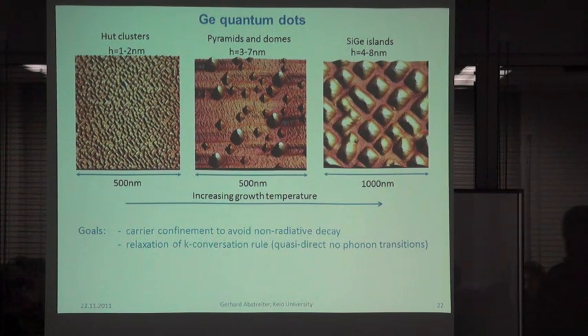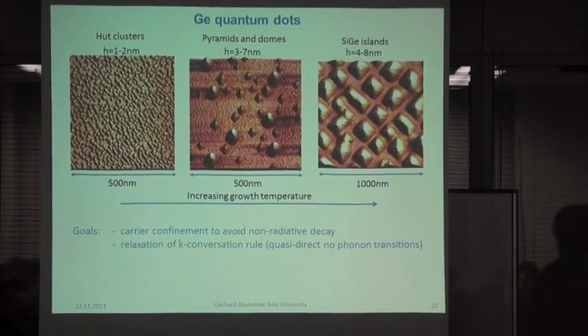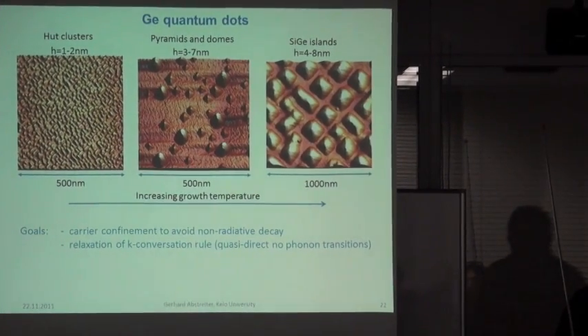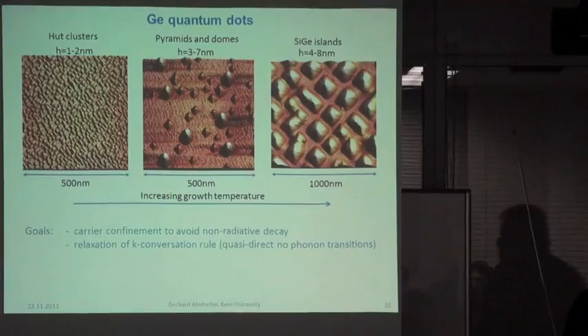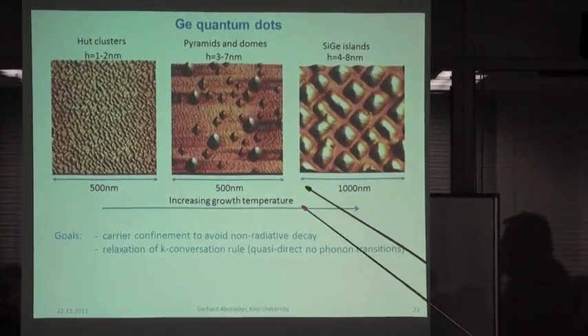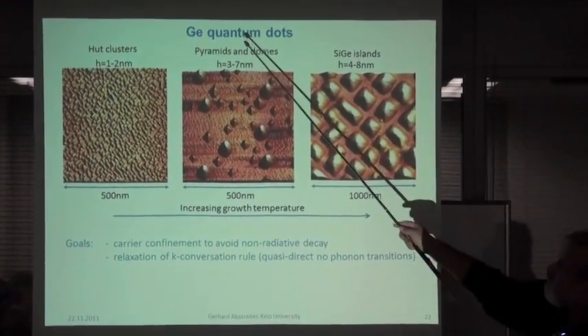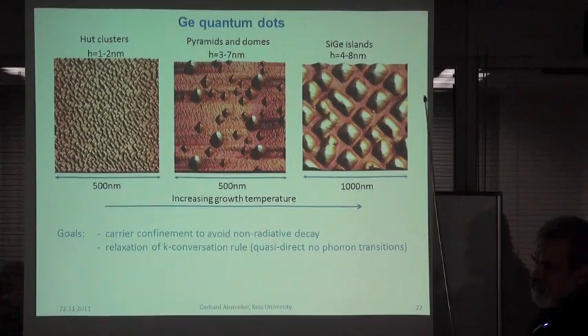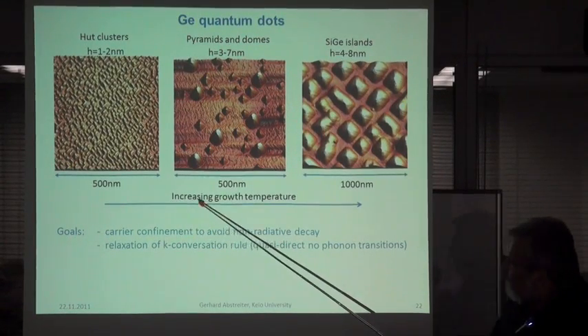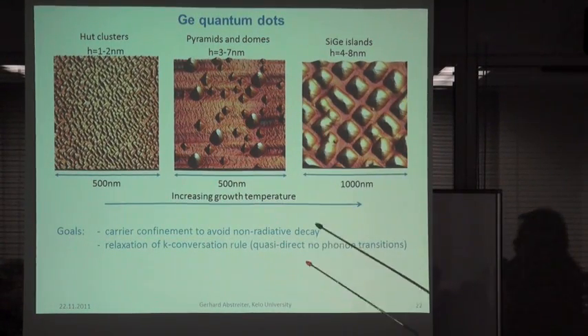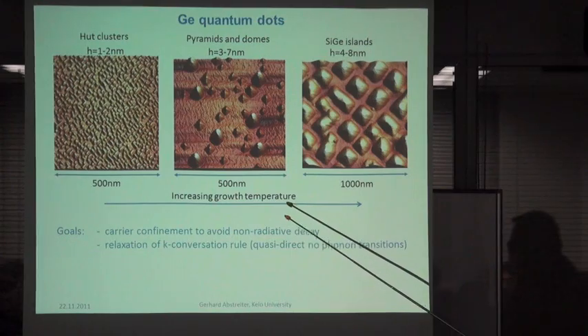Before, I said you have to get a relaxed buffer to get this strained channel. You can do this under certain growth conditions, where the relaxation occurs via misfit dislocations. If you change the growth conditions, and especially if you have a high germanium concentration, then you form islands. This depends on the growth temperature typically, and other parameters, but mainly growth temperature.